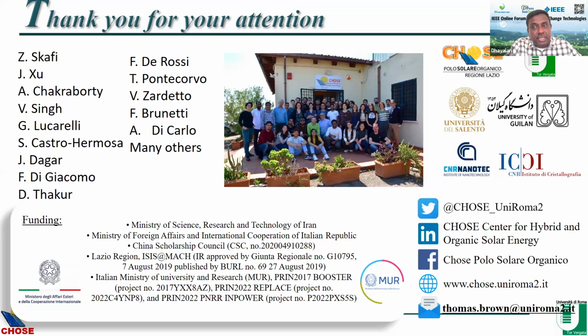But in general, perovskites are sensitive to UV radiation, or is it easy to tune them for UV radiation? Well, yeah, they are sensitive to UV radiation. And in fact, the best way to use perovskite even for outdoors is probably to put some UV filter. Does UV light affect the stability of the material? Yes, UV can affect it, but especially in combination with water vapor and other ingress of gases.